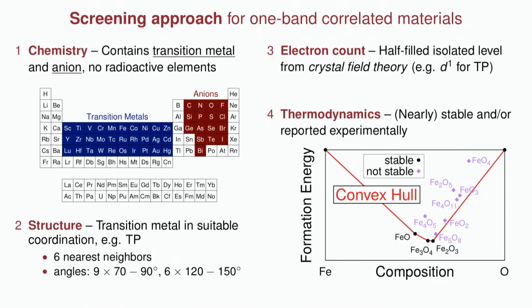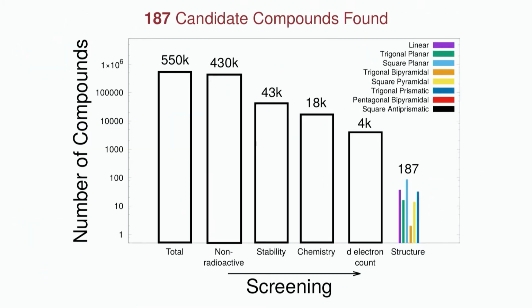So when we implement this strategy, what do we find? In terms of absolute numbers, here I plot the number of compounds we find. This is on a log scale, or you wouldn't be able to see it as I screen, going from left to right. So we start out with all of our known materials, this kind of so-called haystack. So this is 550,000 total materials we have in our database currently. We lose about 100,000 when we screen in terms of removing anything that's radioactive. When we consider the thermodynamics, the stability, now we lose about an order of magnitude.